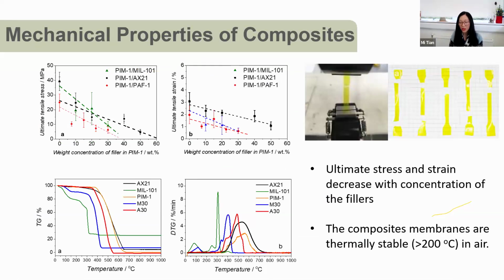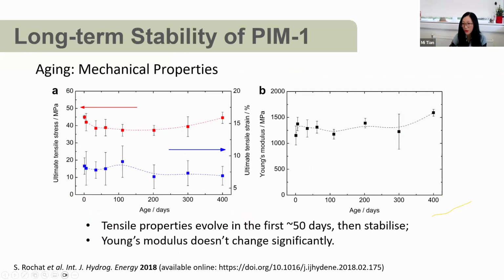Of course, we carried out the mechanical properties of the composite membrane, how strong it is. So we measured the stress and the strain, and we found the stress strain curve decreased with the concentration of the fillers, which is not surprising. And the composite membrane is thermally stable, they can stand beyond 200 degrees C in air, which is really good. Another problem for polymer membranes is aging, degradation. A lot of the polymers degrade over time.